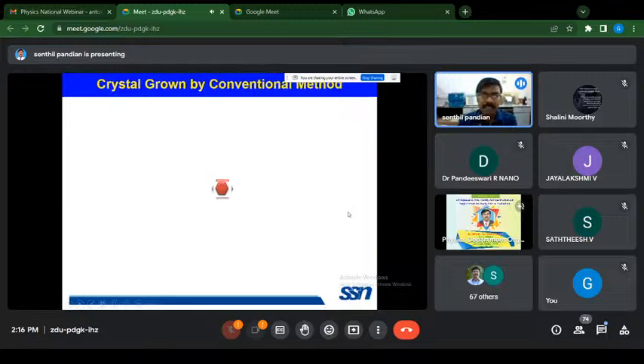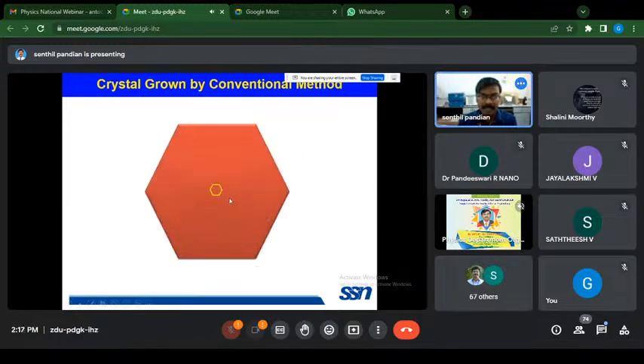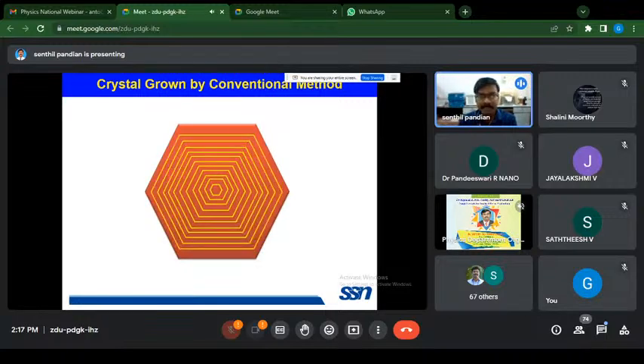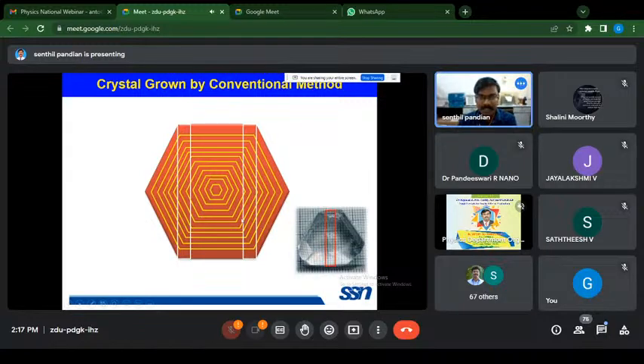In the conventional method, normally the crystal will be grown like this: from small nucleation, then micrometer, millimeter, then centimeter. Suppose in the conventional method, this is the phase matching direction for practical device application. This is the 1 day growth, this is the 2 day growth, the 3 day growth, this is the 4 day, 5 day, 6, 7, 8. You see, there is no uniformity in the conventional method grown crystal.